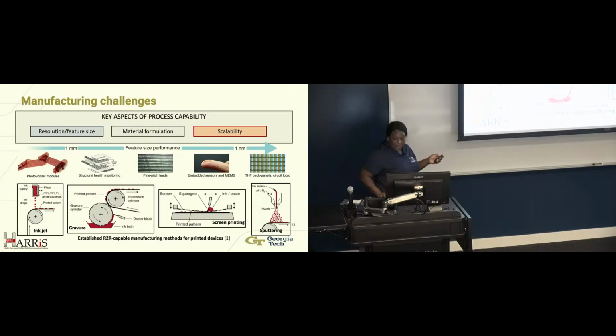So going back to the last technology, the two technologies that we developed, you can see we want printed lines. And if we could get them in different orientations, that would be great. What we would overcome is the complications of inkjet. So it drops, and you have a relatively rough surface. And the question is, how can we make that smooth? We can make that smooth by having a continuous process. Gravure has similar challenges. And then screen printing, of course, you have the line in the screen. That's going to be prohibitive.